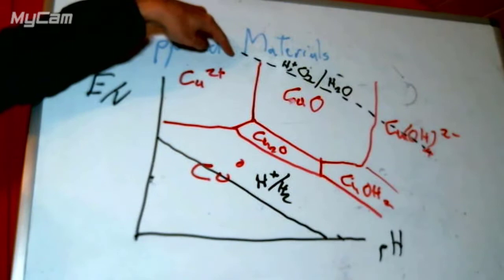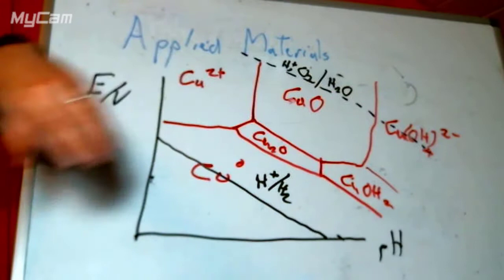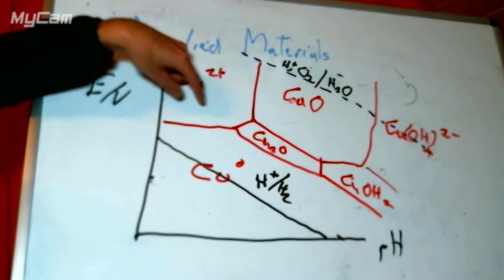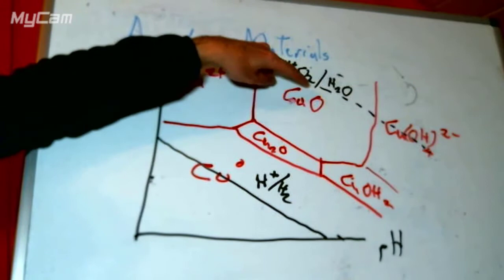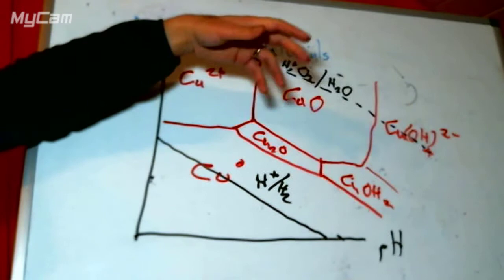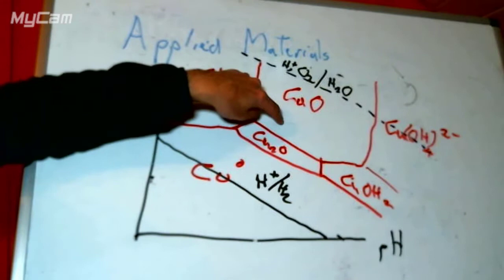If we have oxygenated water, our copper will turn into copper salts. If we have deoxygenated water, nothing will happen thermodynamically. Getting up higher on the diagram, this is copper(I) oxide, and up here is copper(II) oxide. In the case of copper at mid-range pH, our copper will be kinetically stabilized — it will have a layer of copper(I) oxide with copper(II) oxide on top, and it can only corrode at the rate that the copper(II) oxide leaves the surface.